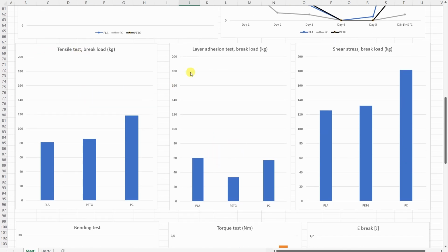Tensile test, layer adhesion test, and shear test. The load is 200 kilograms here, so they are comparable even with each other. And we can see that the polycarbonate was the strongest on tensile test. On layer adhesion test, they are quite equal. Maybe the PETG was a little bit weaker. And on the shear stress, again, the polycarbonate was the strongest.